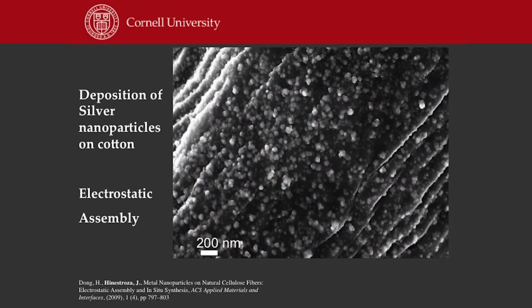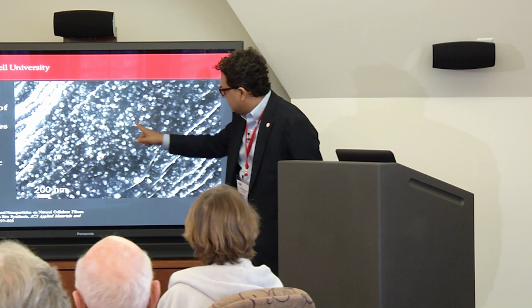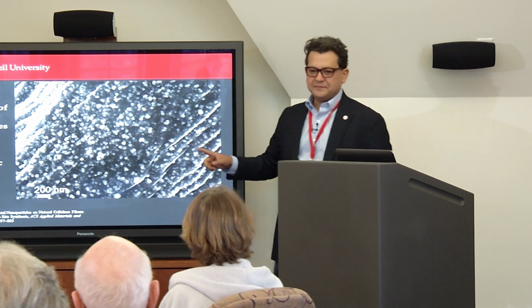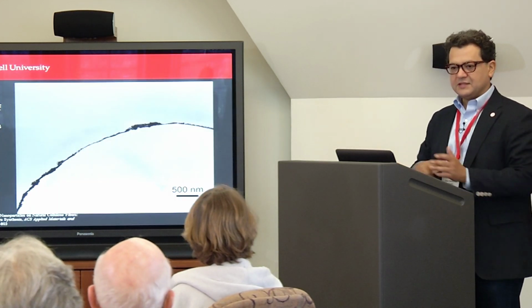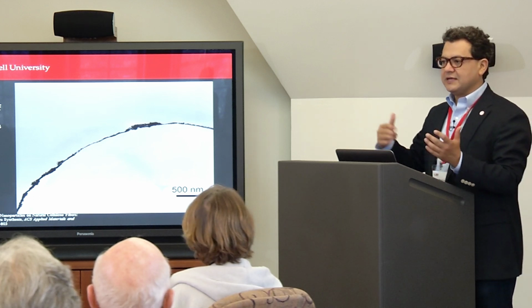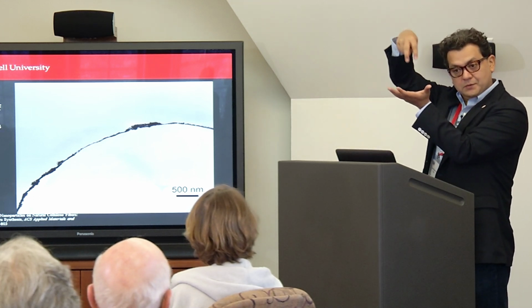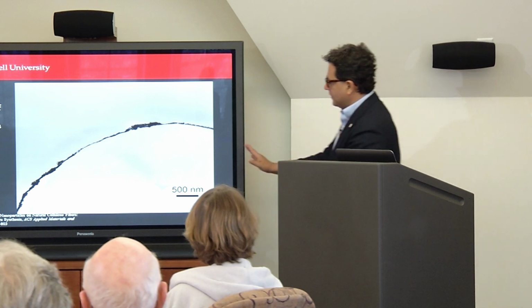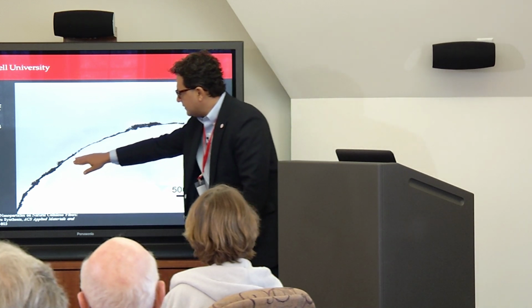Yes? So what this scanning electron microscope does is look at the surface, yeah? So it's looking at the surface, and then you can see the little particles here with the fibers, yeah? And then if I do a cross-section of that, then I use a different technique called a transmission electron microscope. So I see through. And then I can see the fiber of cotton and the particles on the outside, yeah?